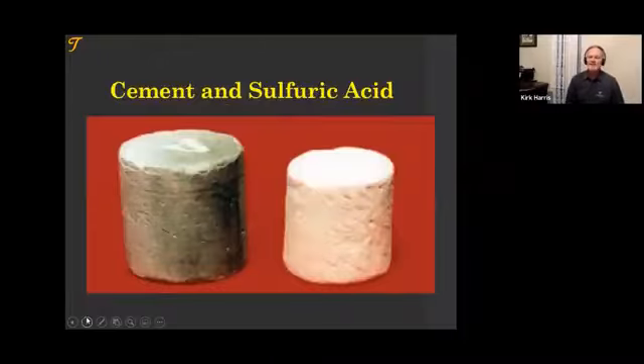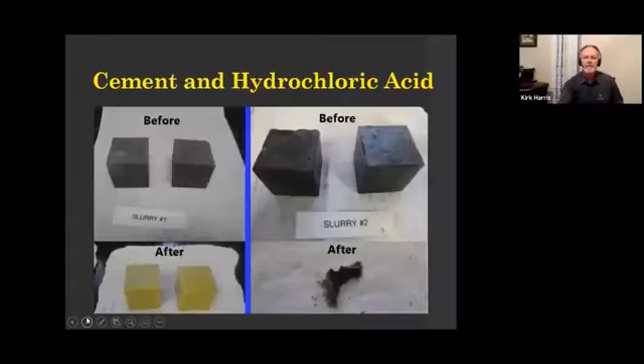These samples were put in the side of a volcano in Sumatra. A sulfuric acid over weeks or months will dissolve the cement. On the left is a corrosion resistant cement. Hydrochloric acid. We tested some samples of hydrochloric acid on cement that melted the cement because some of the additives in that cement would dissolve. We're not acid resistant. We're very acid soluble.